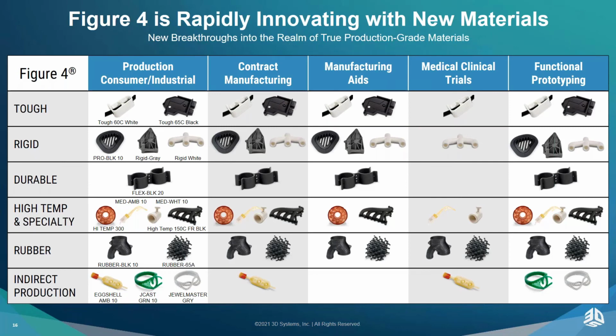The tensile strength is a good indicator, but if you have a low elongation at break to start with, your tensile strength, because of the nature of that ASTM test, is going to tend to track what your elongation at break does. So if you've got one of the high temp or specialty materials, such as High Temp 300, it has a 300°C HDT, but it's only got a 3% elongation. So because it's got that lower elongation, obviously tracking elongation over time, over 8 years, a 1.5% drop is going to give you a 50% reduction in elongation, where really you started as a brittle material and you went to a brittle material. But when you look at the tensile strength, you've got to be careful not to overread that chart, because the shape of that chart is going to be similar to your elongation. So that's where you jump over to your tensile modulus and be sure that your tensile modulus is flat as that moves out based on what that application may be.